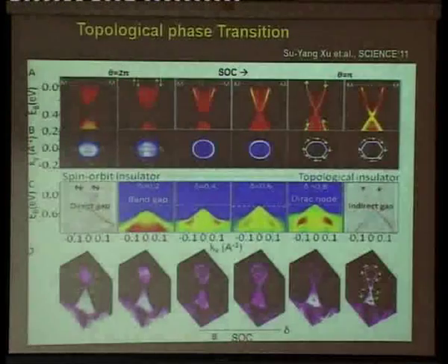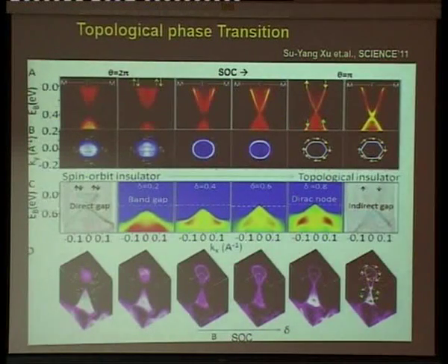These are some more details of that. I'll skip that, unless there's a question. So in other words, we can now look at the topological phase transition. One thing we did not immediately realize is that, for the first time, when you are at the inversion point, you have a three-dimensional Dirac cone. So it would be the real 3D version of graphene. But in this case, it's degenerate. It's not textured. And now we have another paper coming out on that.